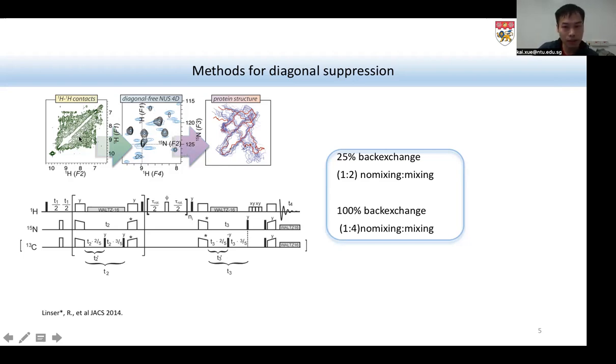So the idea for this scheme is to sum the signals from non-mixing spectra and mixing spectra, and with phase cycling achieve a complete subtraction of the autocorrelation peaks. And they managed to have the spectra completely diagonal free. They stated that for a perdeuterated sample with 25% back exchange, the ratio of non-mixing scans versus mixing scans needed is 1:2, and if it's 100% back exchange, the ratio of non-mixing to mixing scans needed is 1/4. The spectra are very nice, and this is a very good scheme, but the downside of it is that extra scans are needed.